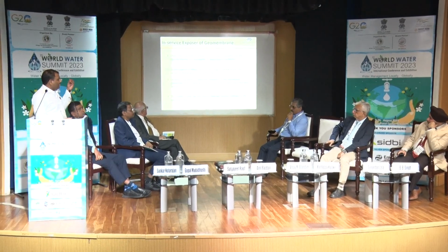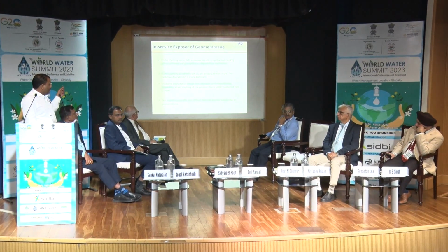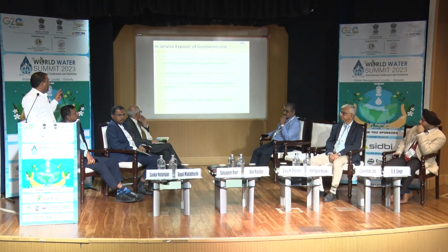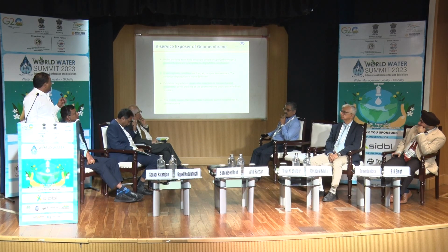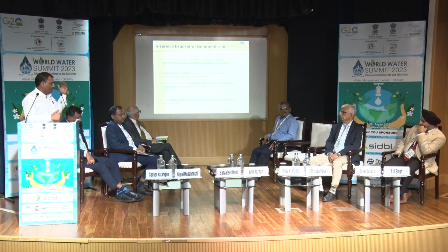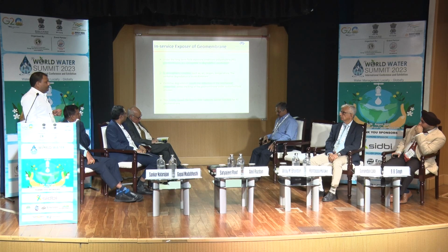Next slide, please. Why is polyethylene not stable for a longer time? Because of the atmospheric conditions and temperature, during the process there is a lot of heat. Polyethylene has a tendency to degrade itself. In the atmosphere, basically oxygen is the main culprit for that, along with the temperature during the process and after the process as well, and it can reduce the mechanical strength of the material. Once the mechanical strength is reduced, the basic role of the geomembrane as a hydraulic barrier is going to be reduced. To avoid this, we need to define the recipe to overcome this process of oxidative degradation. And this overcoming process we measure with the different test methods which I already explained in the previous slide. Next slide, please.